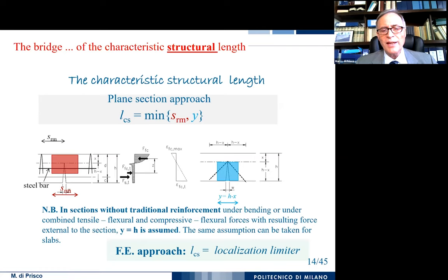Of course, we need to pass from a stress-crack opening to a stress-strain. And this is a very crucial point. So we need to introduce a characteristic structural length. And generally, it is introduced as the minimum between the crack distance and the y, which represents essentially the depth of the beam minus the value of the neutral axis. So if we have a neutral axis which is very close to the upper bound, we can confuse, if you like, the h minus x with the global depth of our cross-section.